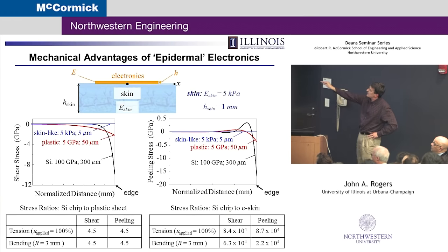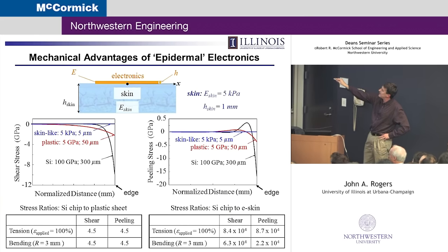So the first thing you see is that the stresses are peaked at the edge of the system, which is what you would expect. And then you can assess the differences between a conventional silicon wafer-based circuit, 100 gigapascals, 300 microns thick; plastic, this is conventional flexible electronics, so it might be a piece of Kapton, 5 gigapascal, 50 microns in thickness; and then skin-like, epidermal, 5 kilopascal, 5 microns. So the trend is what you would expect. You have the largest shear stresses with the silicon chip. You do a lot better with plastic. You go to skin-like, it's even better.